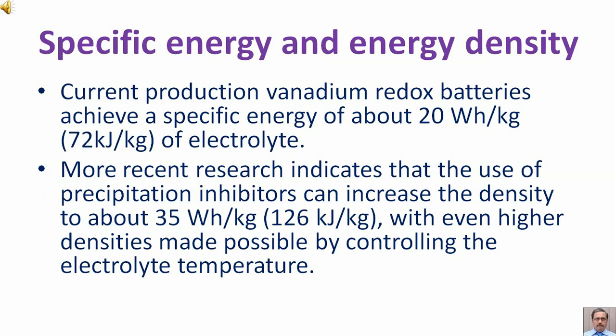Specific energy and energy density. Current production vanadium redox batteries achieve a specific energy of about 20 watt-hour per kilogram of electrolyte. More recent research indicates that the use of precipitation inhibitors can increase the density to about 35 watt-hour per kilogram, with even higher densities made possible by controlling the electrolyte temperature.